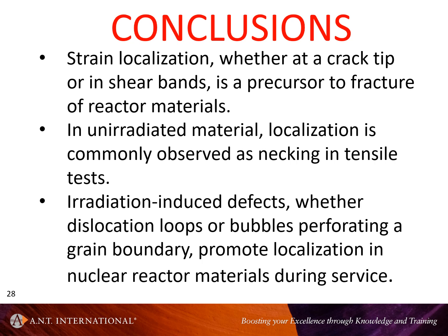Just to conclude, strain localization, whether at a crack tip or in shear bands, is a precursor to fracture of reactor materials. In unirradiated material, localization is commonly observed as necking in tensile test. And irradiation-induced defects, whether they're loops or bubbles perforating a grain boundary, promote localization in nuclear reactor materials during service.